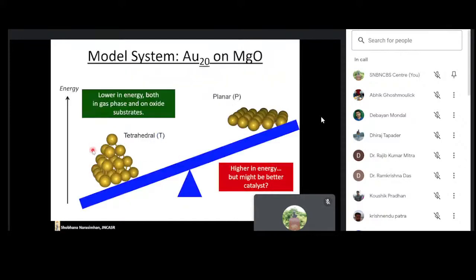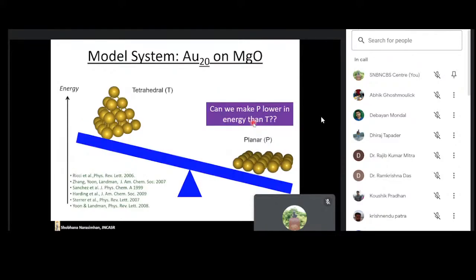So the question we have is, instead of this 3-dimensional shape, can we flatten it and thus make it a better catalyst? So in other words, if I have a seesaw, which denotes the energetic stability, in the gas phase as well as in oxide supports, if I, for example, consider a nanoparticle with 20 gold atoms, it can have this tetrahedral shape, or it can have this flat planar shape. And in the gas phase and on oxide supports, it's this 3-dimensional tetrahedral shape, which is lower in energy. But this one, which is high in energy, there's reason to believe that it might be the better catalyst. So what we would like to do is to tilt this energy seesaw so that this one now becomes lower in energy than this one.